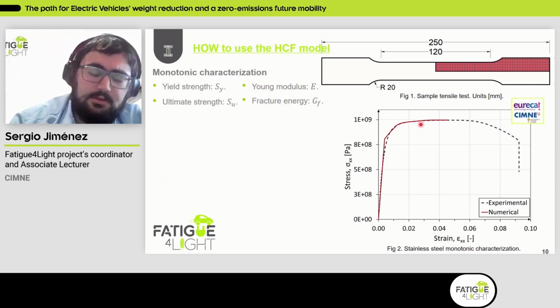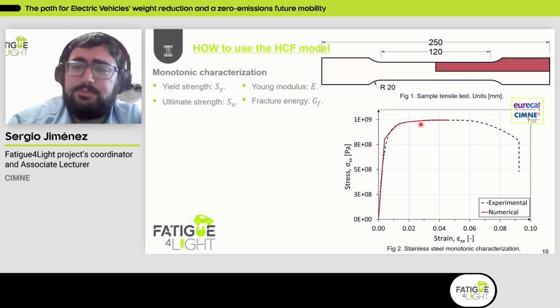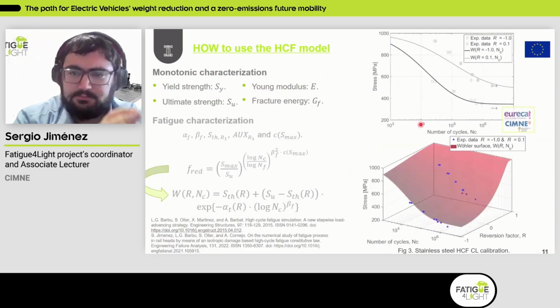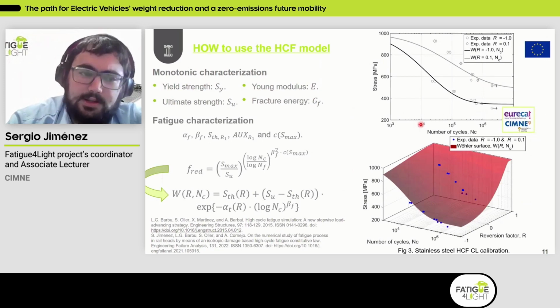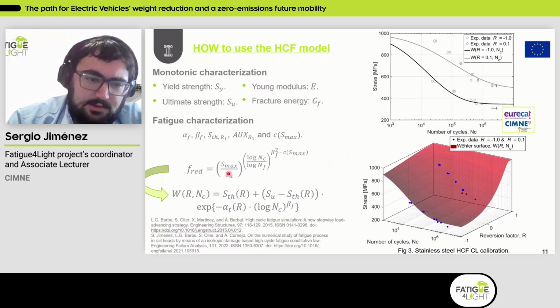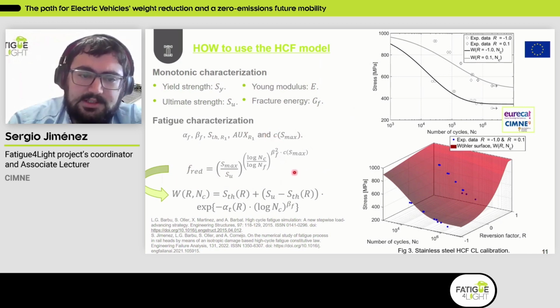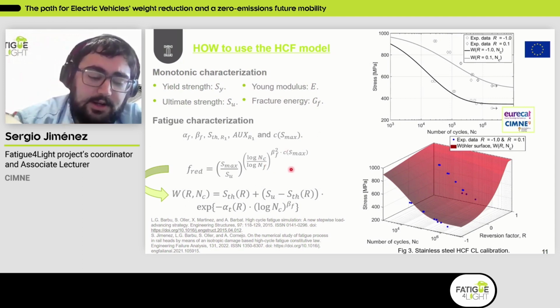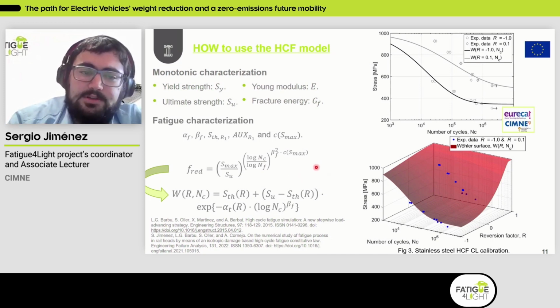And once we've characterized this monotonic response of the material being studied, we move towards the fatigue characterization. And this fatigue characterization means indeed calibrating this fatigue reduction function that I've presented in the previous slides. And this characterization of this function is done by the calibration of 5 parameters here, which define the degradation being followed by the material while applying the cyclic load. And the way in which we do that is